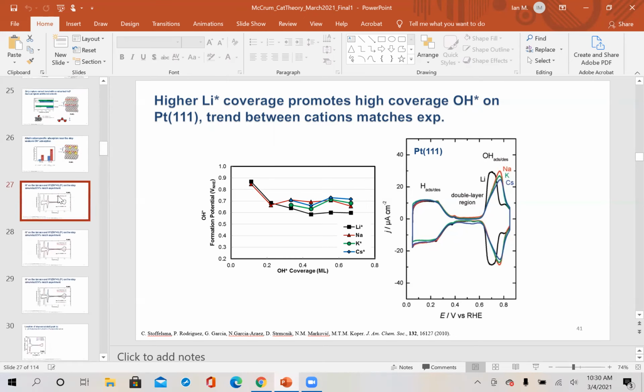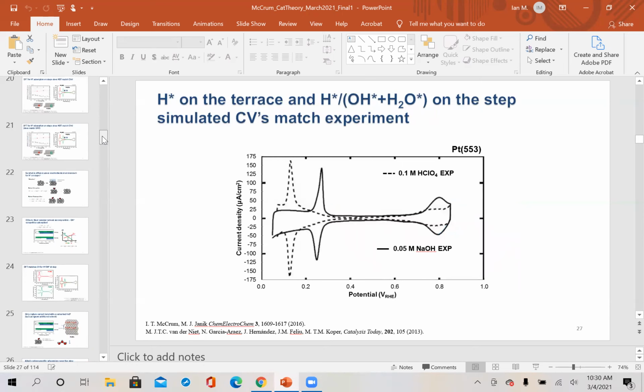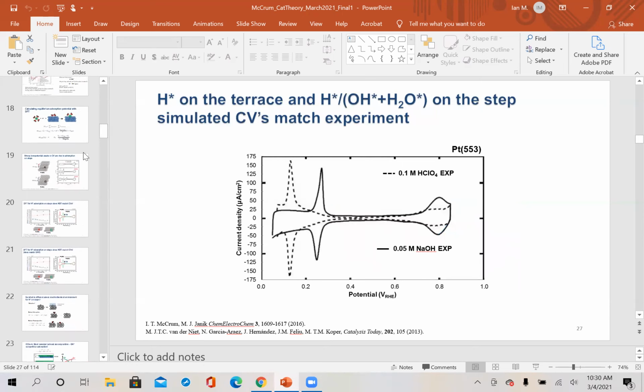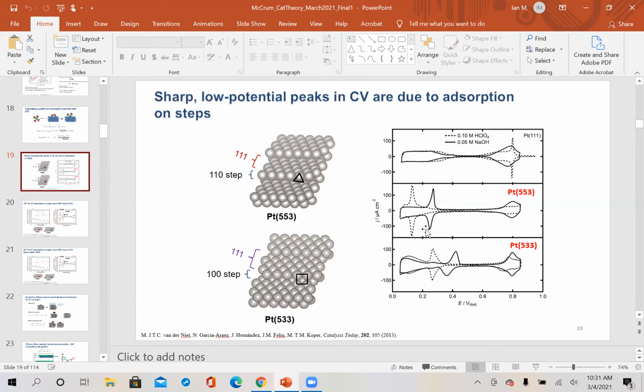So, we do see some hysteresis in some cases on hydroxide adsorption in an alkaline electrolyte. Here, we see for adsorption on platinum 553 in an alkaline electrolyte, the step-associated peak actually shows some hysteresis. And so this is a kinetic effect. If we scan slower, these two peaks come together. We don't capture this in the DFT. We just look at thermodynamics of OH adsorption.